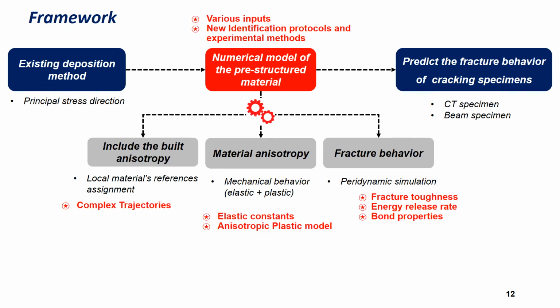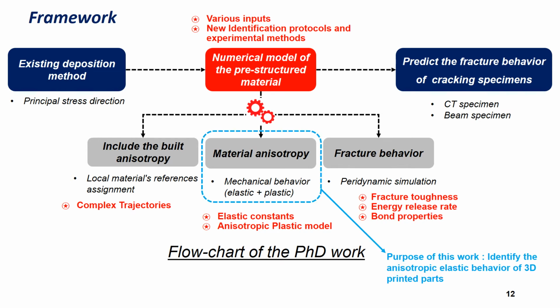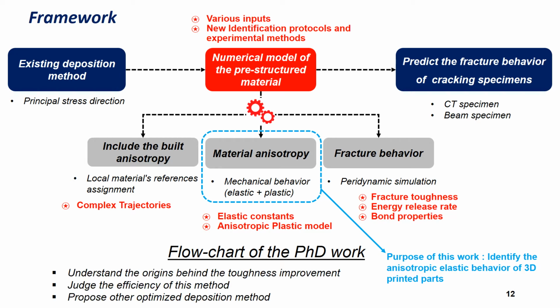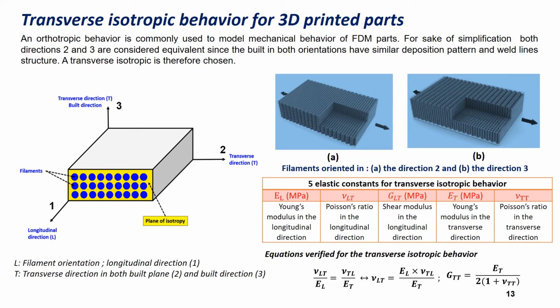Developing a predictive model of pre-structured material presents a challenge, especially identifying the inputs using different identification protocols and experimental methods. Various material constants must be well identified, such as elastic constants, energy release rate and bond properties. The purpose of this work is to identify the anisotropic elastic behavior of pre-structured material using digital image correlation: the longitudinal and transverse moduli, in-plane Poisson ratio, in-plane shear modulus, and the Poisson ratio in the isotropy plane.